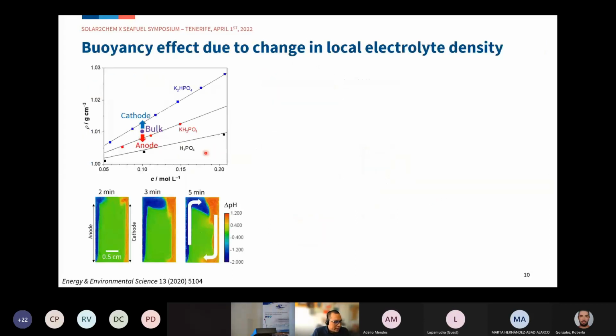One possible explanation is the change in local electrolyte density. Our bulk buffer has a density indicated by this purple point, and as the cathode becomes more alkaline, it moves towards this direction, becoming heavier. This explains why the electrolyte goes down near the cathode. But at the anode side, as it becomes more acidified, it becomes lighter, which explains why it goes up.